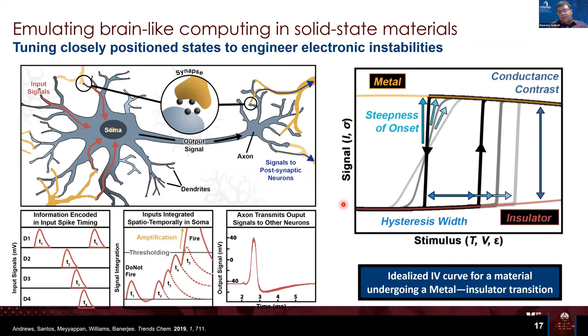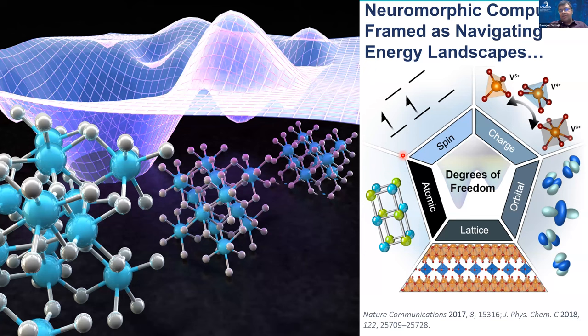And then as part of this, again, I touched upon this at the beginning, how do we disentangle and get some control over these transformation characteristics? Because subtle differences in the steepness of onset, in the conductance contrast and how sharp this is, strongly affect the function of the oscillator or any other device you're going to try to build. And so being able to control material properties, just like you can control silicon properties, is really key, but is again very, very non-trivial for most of the systems.